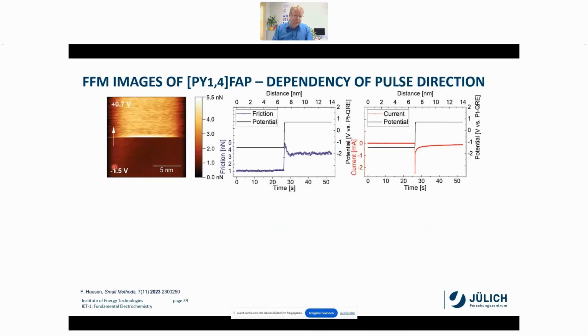And the result you see here. So that is again switching from minus 1.5 volts to positive potentials, recording the potential. You see that here, changing the potential from minus 1.5 to plus 0.7, as indicated here as well, and then in parallel recording the friction force. And you see when we change the potential, we have a change in the friction, which then decays again and then stabilizes over a long time.